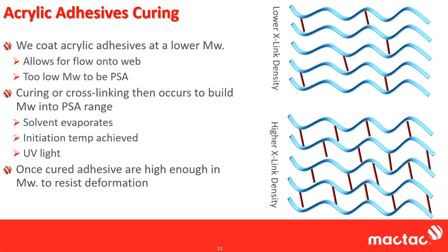So how we get an acrylic adhesive onto the web is we coat it on at a very low molecular weight, much lower, far too low that would ever make a good adhesive, but it does allow us to get it onto the web. And then we cure that adhesive, sometimes called cross-linking. And this happens in 3 different ways.